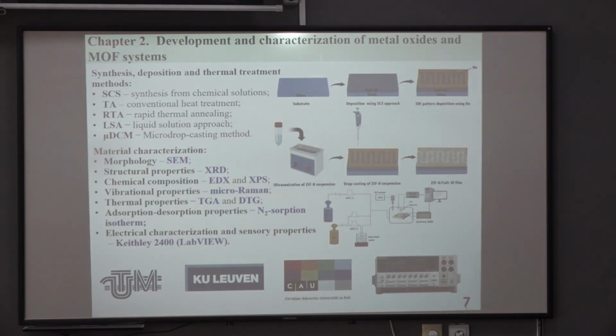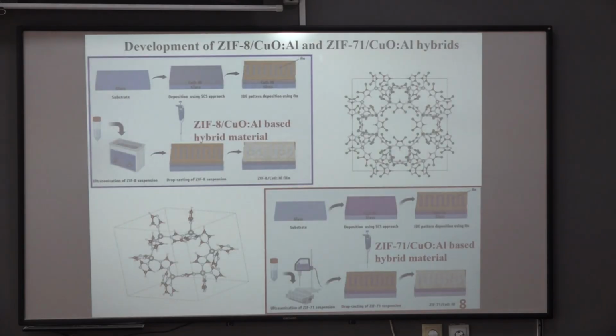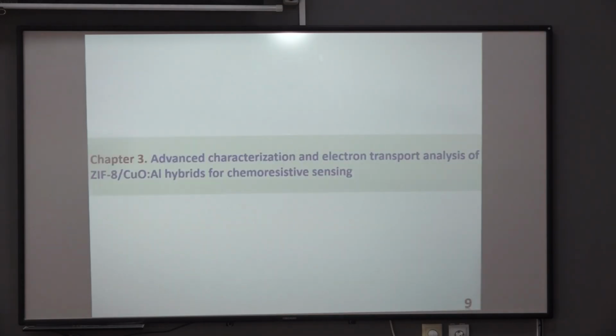This schematic shows the development of hybrid systems, starting with the glass substrate, followed by copper oxide aluminium synthesis using the SCS approach, followed by gold IDE patterning for the electrical contact, followed by ultrasonication of ZIF dispersion and micro drop casting of it on the developed metal oxides. This is how the development of the hybrid system occurred.